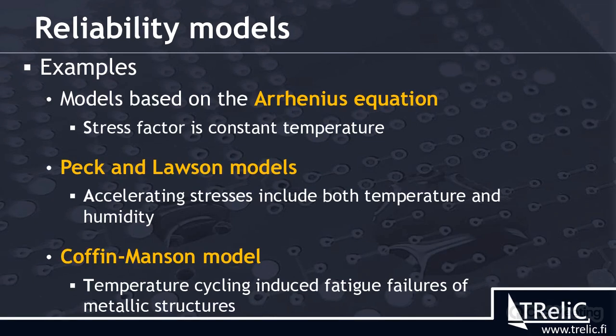Another model which you can check, for example, is Peck and Lawson models. Here both temperature and humidity are considered. This is also quite general, but it's one model which can be used in these cases. Then Coffin-Manson is very common for temperature cycling, fatigue failures of metallic structures. It has been very commonly used, and it's a basis, for example, for most of the models used in solder joints, which I was talking about, because they are metallic structures and can be modeled like this. So Coffin-Manson is the one behind them.